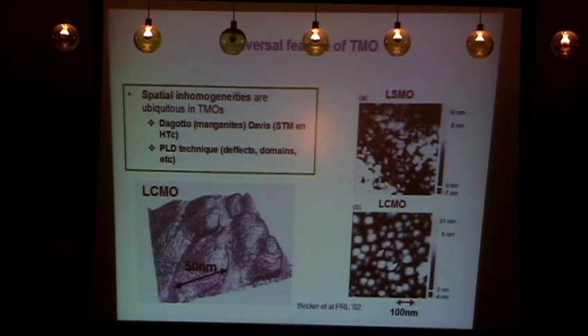On top of that, there are thin films, which also opened the door for the rejuvenation of this field. The thin films are fabricated using techniques like pulsed laser deposition, which sometimes generate systems which are not completely homogeneous, unlike single crystals, and RF sputtering also works. So in general, all different techniques work. An example of even a system which can be made clean but has electronic phase separation has been very much highlighted in the case of the manganites, where these